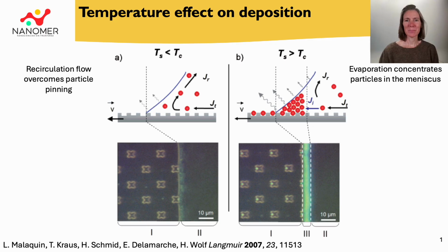The faster solvent molecules leave the meniscus through evaporation, the faster solvent molecules will move from the bulk solution towards the meniscus to replace those that have left. This generates a flow that carries solutes and suspended particles towards the drying line. Perhaps the easiest way to increase evaporation rate is increasing the temperature of your chamber.